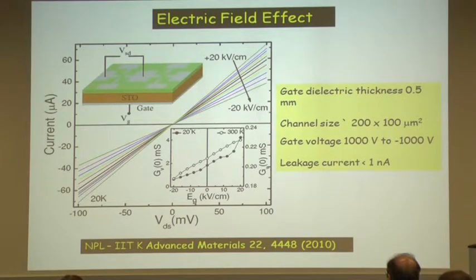And this is how we apply the gate, very simple. What we do is, instead of using a top gate, we use the 0.5 millimeter thick strontium titanate substrate as our gate dielectric. We metallize it from the back, and then we can apply really brutal gate fields, from 1,000 volts to minus 1,000 volts. You wouldn't like to do that in your cryostat, but this works beautifully because the gate dielectric is very robust. So even at 1,000 volts, the leakage current is negligible. One would like to apply a top gate so that you can work with 5 to 10 volts. Unfortunately, the top gate does not work. The leakage current is always very high.